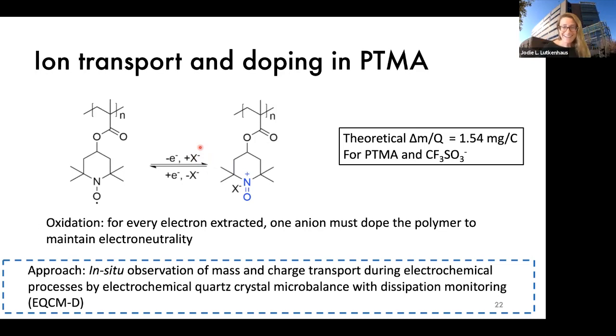All right, so anyway, we have this anion transporting from the electrolyte into the electrode and vice versa as we reduce and oxidize. So if our electrolyte is lithium triflate, then the anion we're transporting becomes this triflate anion. And you can actually calculate for every coulomb of charge that I pass, what would be the change in mass of the electrode due to the anion transport. So this theoretical value is 1.54 milligrams per coulomb, and we're going to be comparing against that.